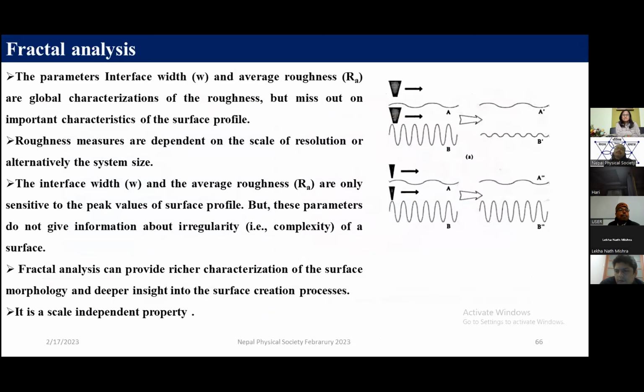Now come to fractal analysis. Classically we were using parameters like interface width and average roughness, the global characterization of roughness, but they miss important characteristics of the surface profile. What is happening on the surface is missed. One can see two cases here. If your probe is larger than the features, it will obtain this type of structure, and if it is very narrow, then also it is not suitable. The interface width and average roughness are sensitive only to the peak values of the surface profile.